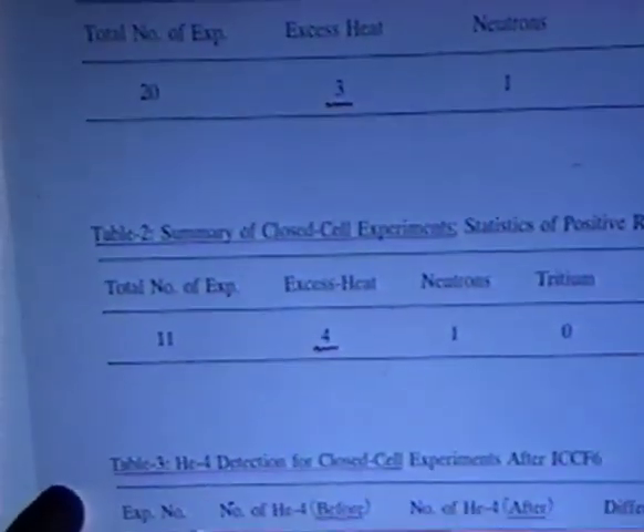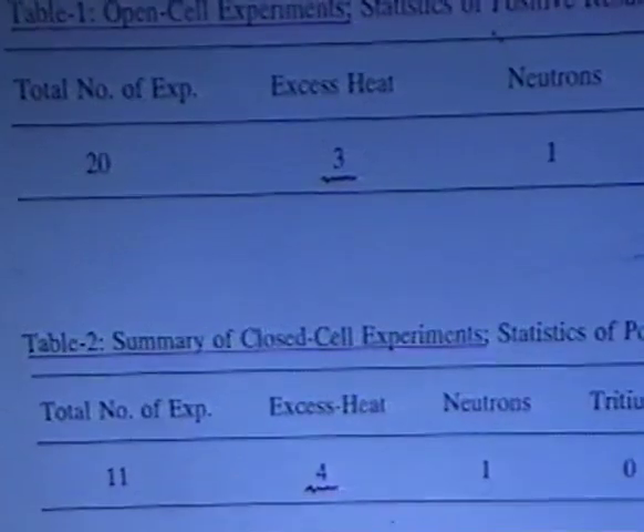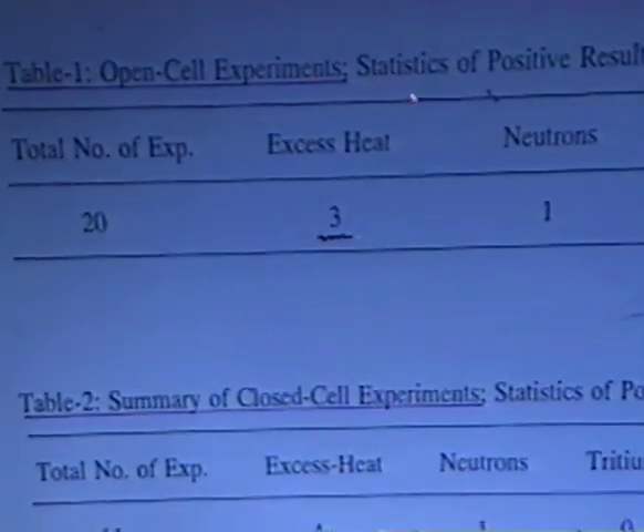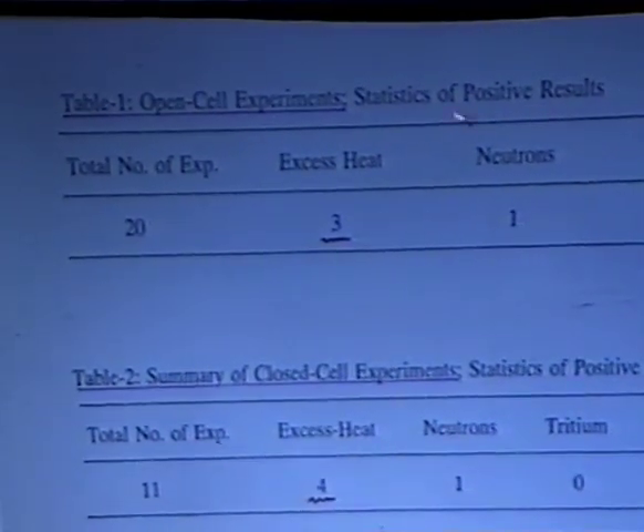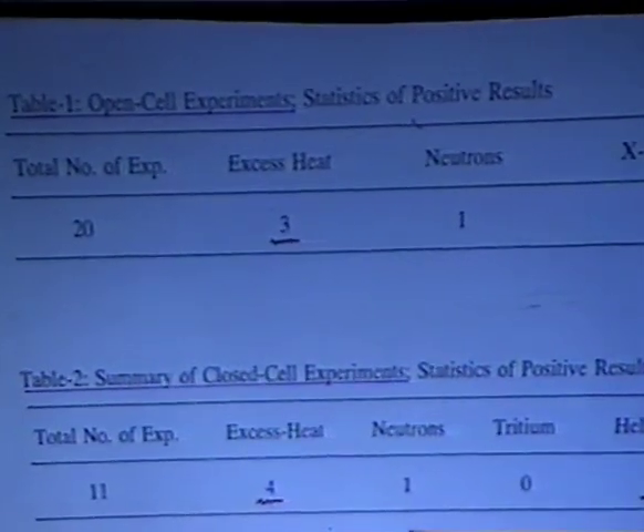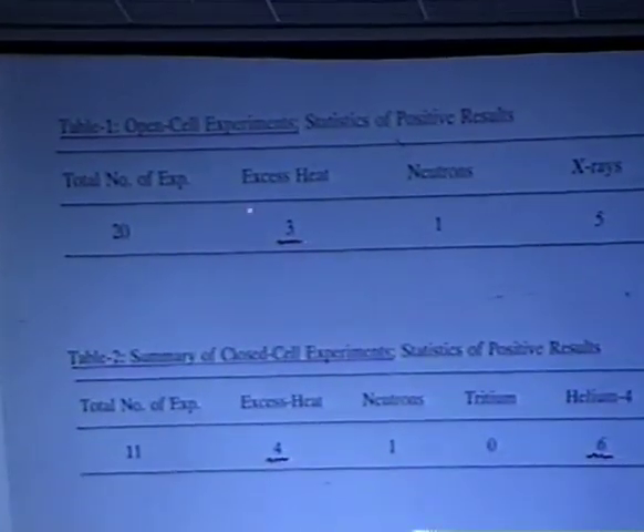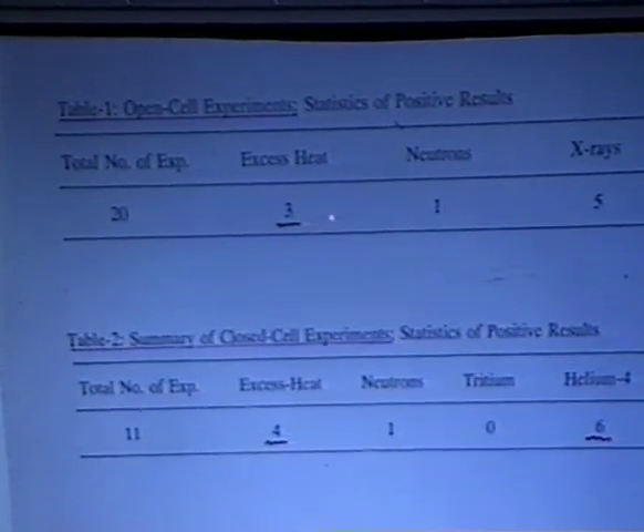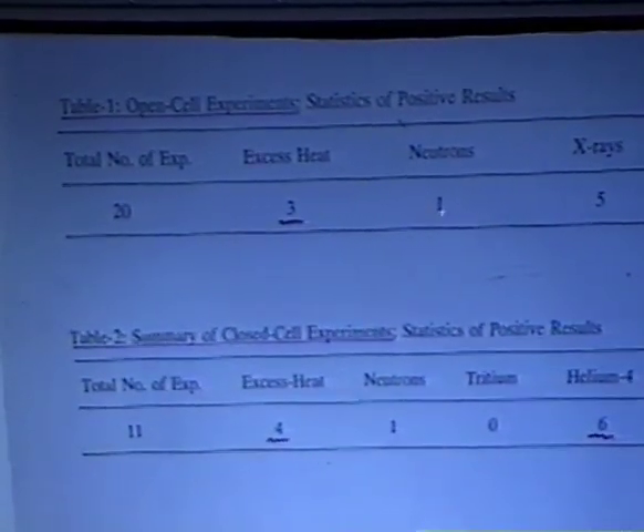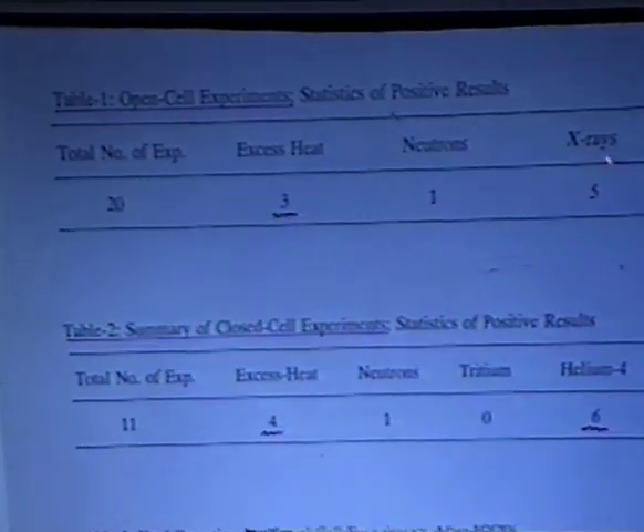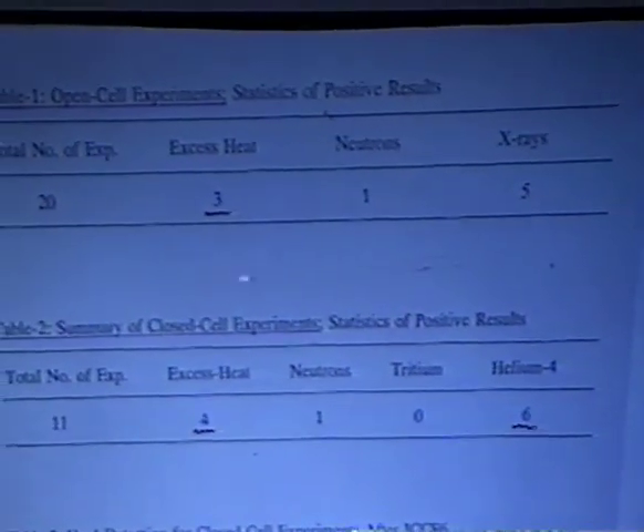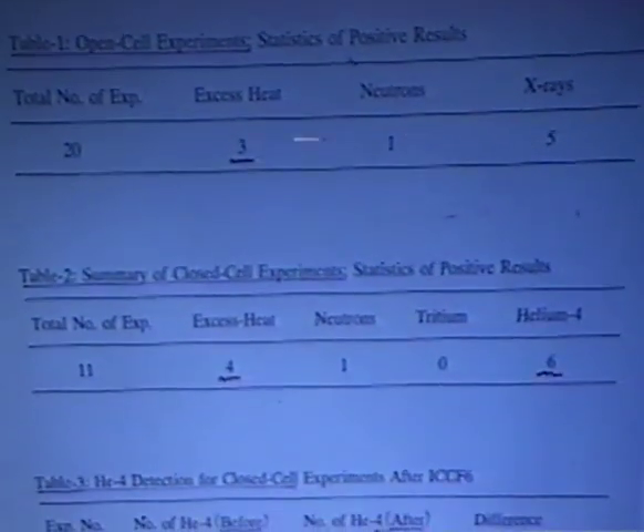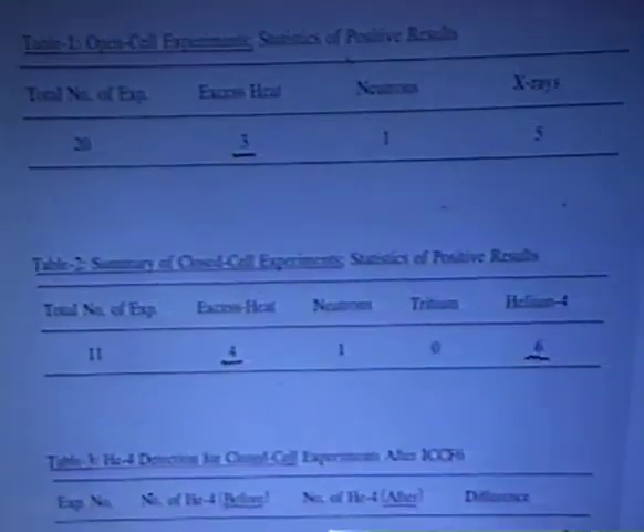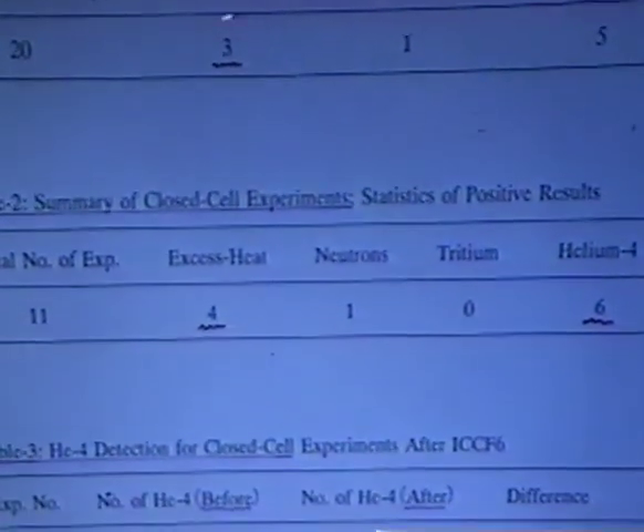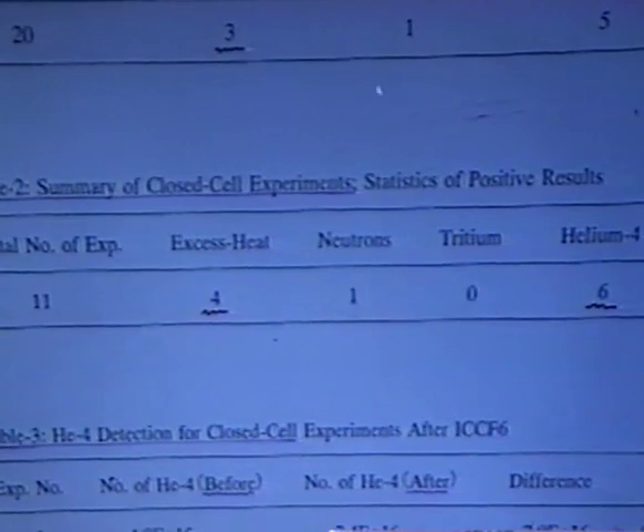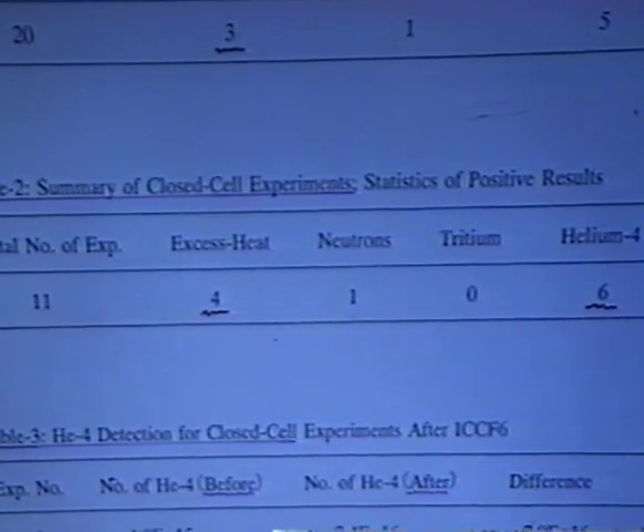So let me summarize the results of the electrolysis experiments, the open cell experiments. This is the statistics of positive results we have obtained. Out of 20 experiments, we observed only 3 positive excess heat, 1 neutron, somewhat meaningful, and 5 X-ray signals, but without any correlation between these events. So we don't see any correlation between measured excess heat and nuclear radiation in this case of open cell.